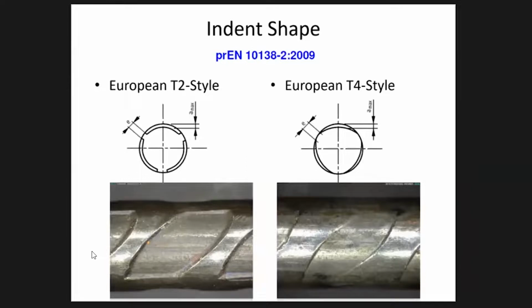The T4 style indent tends to be deep in the middle and taper out. So when we look at that, we have an edge in the middle, and that tapers out. I think that actually is an easier wire to produce without causing issues, because when you use a T4 style wire, you can withstand almost twice the depth variation than you can with a T2. If you have a depth variation on a T2, it affects that plowing area directly. On the T4 style, you get a factor of 2.